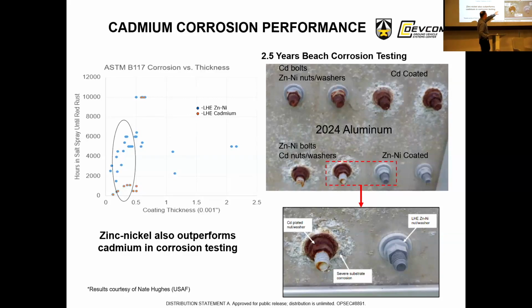I mean, this picture right here on the right kind of speaks for itself. You have the cadmium plated and the zinc nickel, and you can see the difference in terms of the red rust. And look at how the zinc nickel is holding on very well. The LHE, that stands for low hydrogen embrittlement. And same thing here, for the coating thickness, when you look at 0.5, you can see the LHE for zinc nickel outperforms the LHE for cadmium by about 5,000 salt hours. So it's just superior. When you look at zinc nickel to cadmium, it's superior as well.